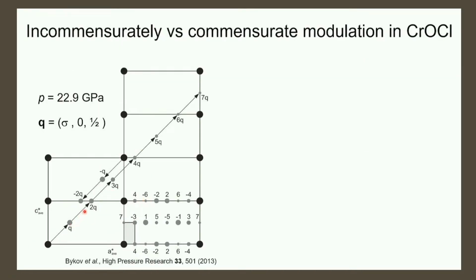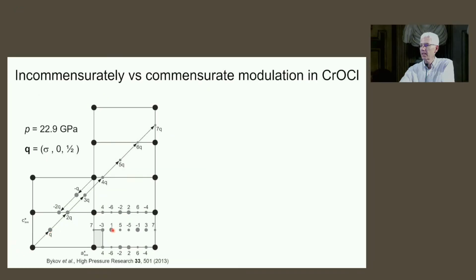So here is how we would index 1Q, 2Q, 3Q, 7Q. We are halfway. That's this half, which doubles everything, and it reaches -7Q from the other sides. We can also consider all these superlattice spots in one reciprocal unit cell of the basic structure, and here is the M index. So the 1 is here, that's this one, and the 2 is here, that is this one, and so on. And you see they are nicely separated by 1/7.